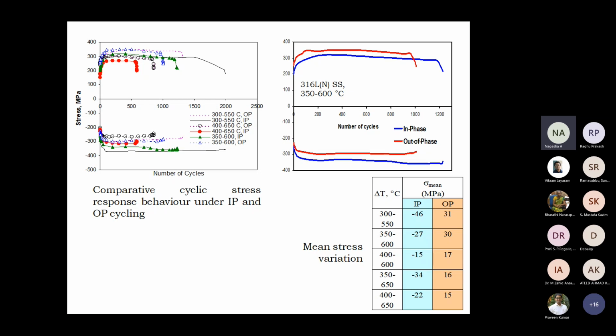Normally the out of phase TMF leads to a tensile mean stress, as against the compressive mean stress observed under the IP cycling. The compressive mean stress under IP cycling arises because the compressive deformation taking place at the lower temperature gives rise to higher stress compared to the lower stress that happens at the maximum temperature, during the IP cycling.